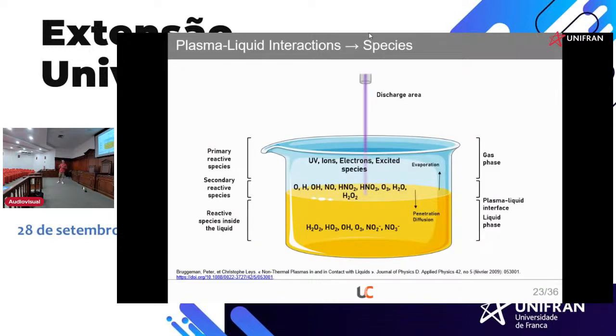And in fact, if we speak about the plasma, what happens? You have your discharge area, and you produce some ions, UV, and excited species. If we are in air conditions, you will produce also secondary reactive species like OH, NO, NO2, etc. And all the particles, due to the flux, are going inside the liquid. So there is a penetration, diffusion with some reactive species inside the liquid, which will lead to the reduction or something else.